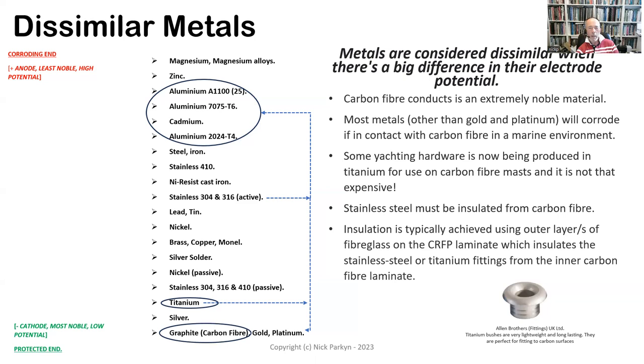And what it does is introduce a shear force into the bolts, or the fastenings, that are holding that particular fitting onto the spar itself, which is not something that you want to be introducing, because then you potentially get a shear failure on those fastenings. Because if you attach it directly and bolt or fasten it hard down onto the surface, you don't get any flexibility at that joint, and therefore you don't get any shear forces introduced unnecessarily.